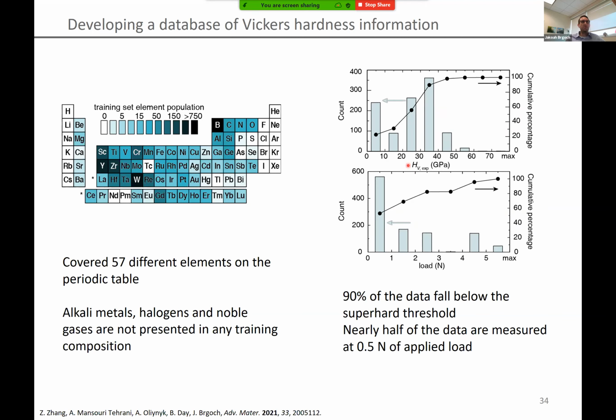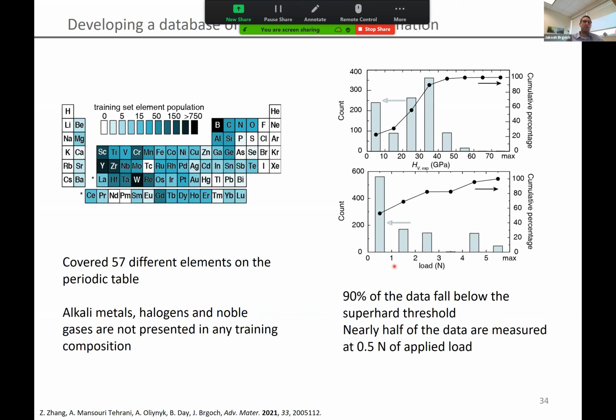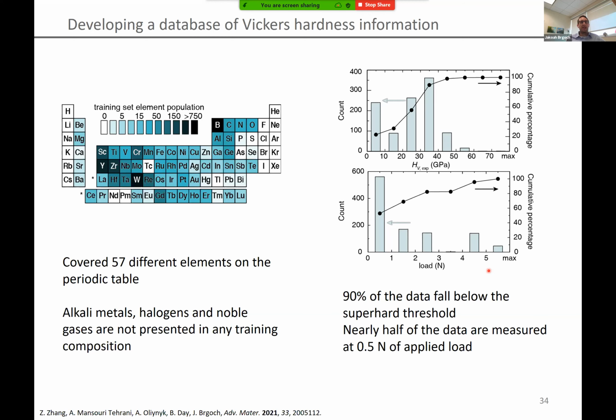So there's no interest in measuring these types of materials. Our data distribution is quite imbalanced—most compounds, almost 90%, fall below 40 gigapascals, but we do have some high hardness compounds. Our load distribution is mostly at half a Newton, but there's some data at higher applied load as well.